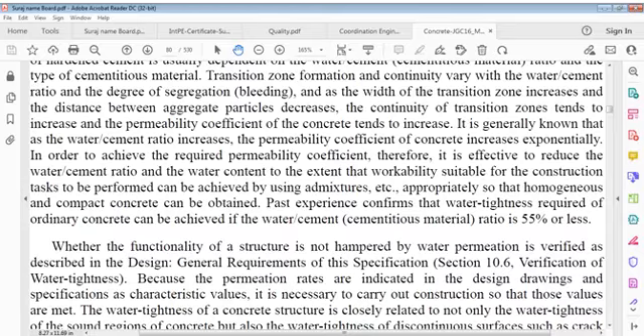Transition zone formation and continuity vary with water cement ratio and degree of segregation, that is called bleeding. As width of transition zone increases, distance between aggregate particles decreases. Continuity of transition zone tends to increase and permeability coefficient of concrete tends to increase. It is generally known that as water cement ratio increases, permeability coefficient of concrete increases exponentially.